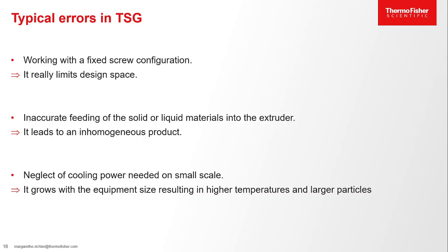Then again, what you see quite often, this bimodal distribution of granules, and people state that this is due to these two screws and so on. This is, frankly speaking, nonsense. You have a bimodal distribution if you have inaccurate feeding, and especially the ratio of liquid to solid. So if your liquid is not well distributed into the granules, you'll not get a good particle size distribution. Therefore, this can lead to an inhomogeneous product, so you get very fine material and then again very large material, but nothing in between. So this is really something to look into. Feeding is very crucial in twin-screw granulation.